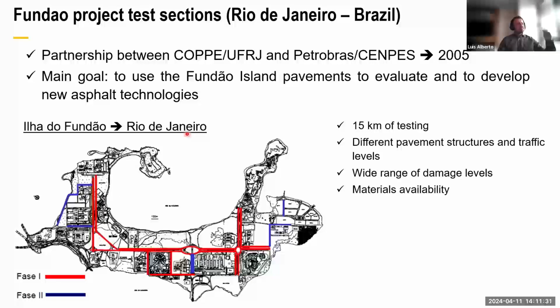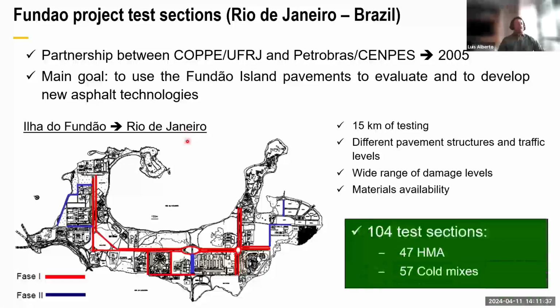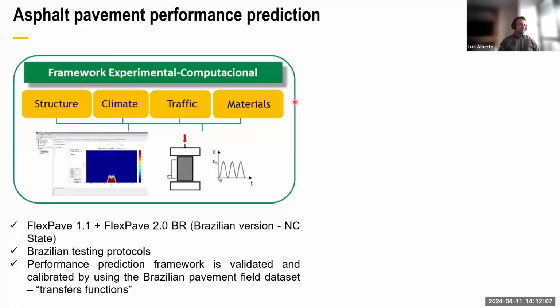Here is a kind of cradle of the project, a localized one. In this project, we could build 47 hot mix asphalt test sections. It's a very nice one. Even though we have only one climate and one traffic condition, we could test different materials. So it was very nice to learn from the materials. First we learn from the materials in this local experiment, and afterwards we could expand to the national ones.